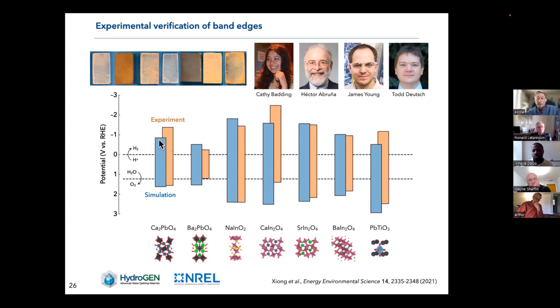And so what you can see here, based on those DFT calculations, those quantum mechanical simulations, is that we predict that those materials will have a suitable band alignment, meaning that the top of the range of energy is above the energy of an electron in water, and the bottom here straddles the lower bound for the energy of an electron in water. And so now the question is, experimentally, what do we get?